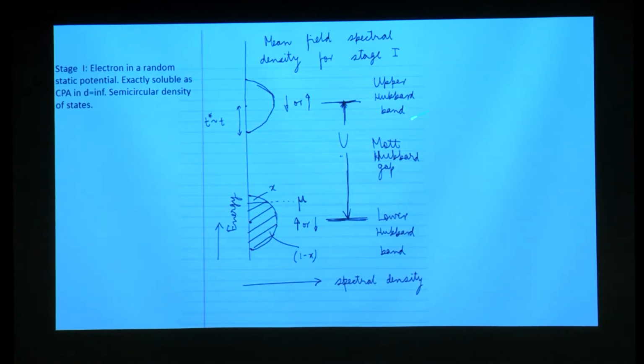If you look at that, then you find that there is a spectral density. This problem also cannot be solved exactly, but it can be solved in the d equal to infinity limit, in which case the coherent potential approximation, or CPA, is exact. That is, the problem of an electron moving in a random potential can be solved exactly in infinite dimensions. And there is a fair amount of experience which says that those results are reasonably all right for 3 dimensions and so on. So in that case, you can solve it exactly, and you find that you have a semicircular density of states, and there is a Mott-Hubbard gap.